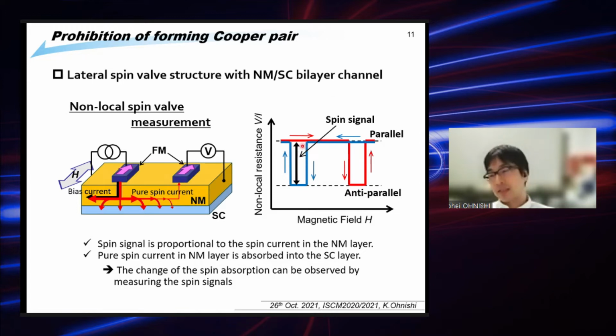The spin signal is defined by the difference of the non-local resistance between the parallel state and the anti-parallel state. This spin signal is proportional to the detected spin current. So if the pure spin current is absorbed into the superconducting layer so much, the detected pure spin current should be small, so the spin signal also should be small. But if the pure spin current is prohibited from being injected into the superconducting layer, almost all the pure spin current can reach the detector. In that case, the spin signal should be very large. In this way, we can detect how large an amount of the pure spin current is absorbed by the superconducting layer.